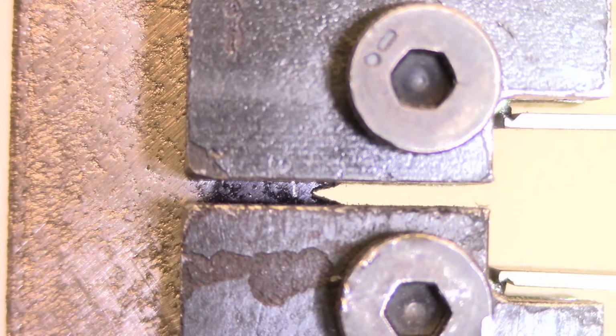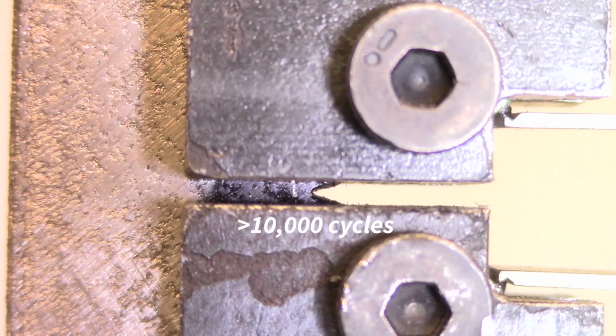So I've stopped the cyclic fatigue pre-cracking. It's difficult to see now, but we do have a pre-crack. I'm going to jog up just a tiny bit, and you can start to see that crack separate at the root.